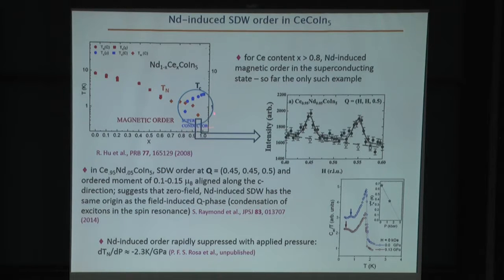So this neodymium-induced spin density wave has exactly the same character as this field-induced so-called Q phase in pure cerium cobalt indium-5, and suggests that both of this magnetic order, neodymium-induced order, as well as the field-induced order, have the same origin, namely the condensation of excitons in the spin resonance. So this magnetic order in the superconducting state appears as a very small anomaly in AC heat capacity divided by temperature. This large anomaly is the superconducting transition temperature. Here's the small anomaly associated with the spin density wave order. And Priscilla has shown that this spin density wave order is very rapidly suppressed with applied pressure. And we'll come back to this point in just a couple of slides.